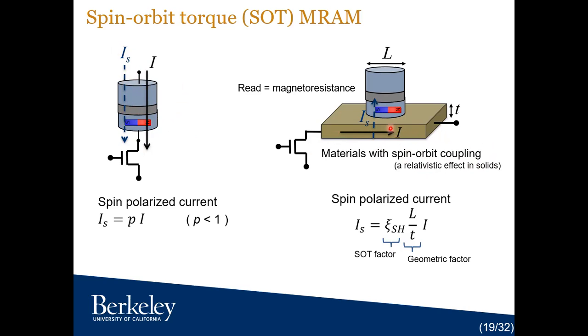But here we are utilizing a different effect. Some people call it spin Hall effect, and there could be other origins for that. But the fact is, if you run a current in one direction, you will have a spin current in the transverse direction. So if you have your MTJ right on top of it, you can switch this free layer, and that's reversible because if you reverse the current, your spin current also reverses.